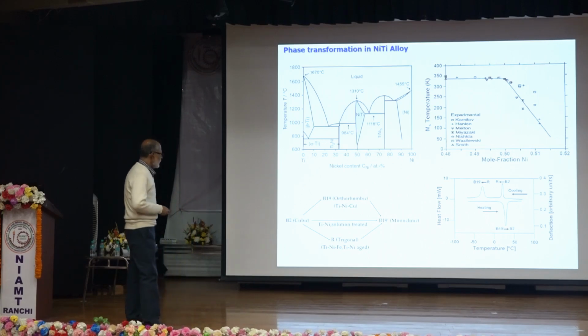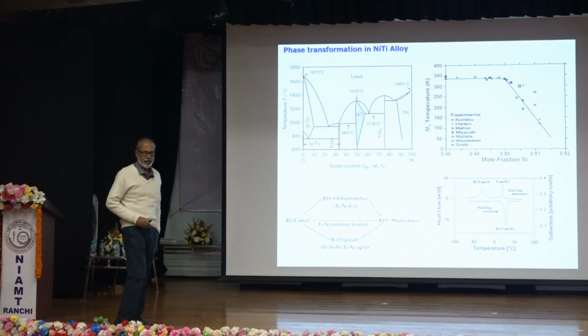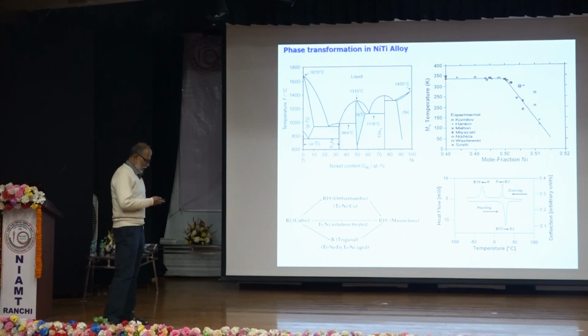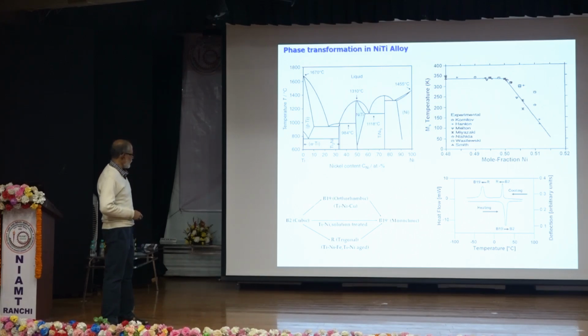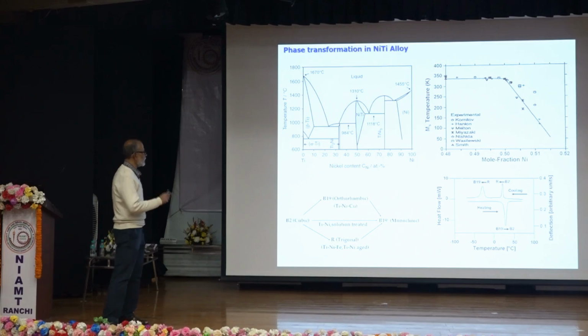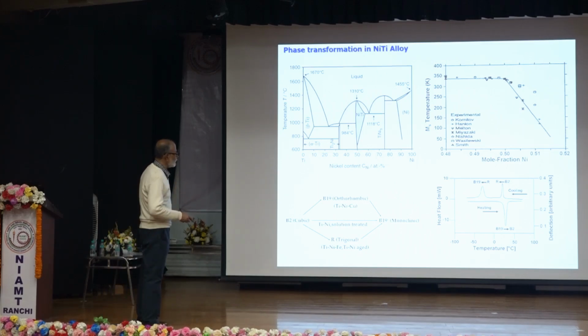Now, it has also been found that if for some reason martensitic transformation is constrained, either by strain or by certain barrier, it can take an alternate path. B2 austenite, the high temperature phase, is cubic. The low temperature phase, we call it B19', is an orthorhombic phase. It can happen directly, but it can also take a different path where an intermediate, pre-martensitic phase forms, which we call R phase. And why I am mentioning this, I will come to that. And this is also verified by DSC experiment.